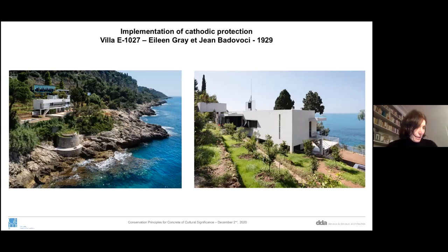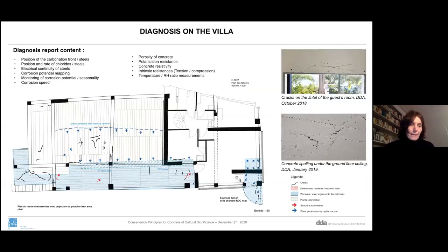The Keeping It Modern grant we got for the restoration permitted us to do a very intense analysis and diagnosis. We started in 2014-15 the diagnosis. There was another restoration done already in 2006-2009, but cracks reappeared very quickly. So we started a new campaign to analyze the carbonation front, the rate of chlorides and sulfates, the monitoring of the corrosion potential, and a lot of other diagnoses and analyses.